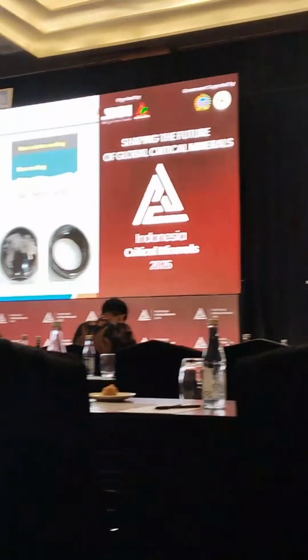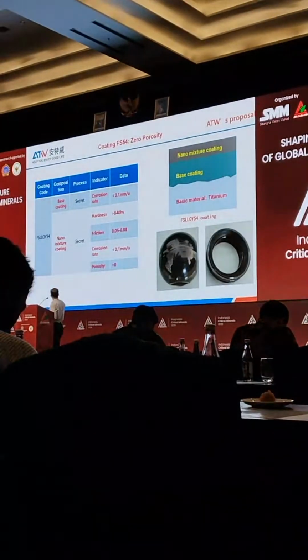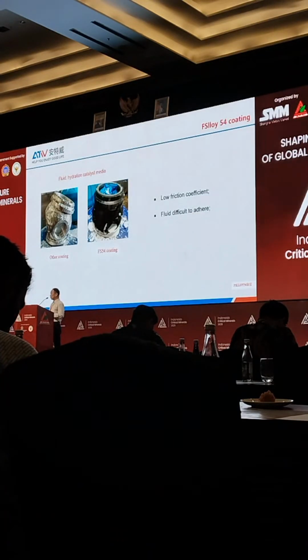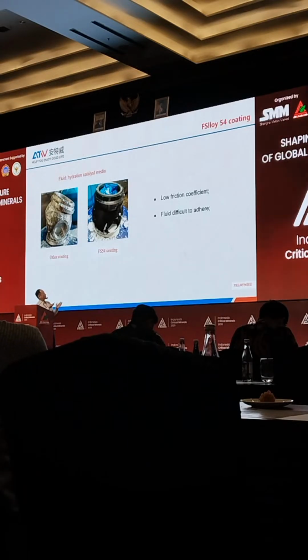And around three years ago, we finally found the coating, which we call FS54. Its corrosion rate is below 0.1 millimeter a year. Its hardness is over 840 HB, and its friction coefficient is around 0.05 to 0.08. And its porosity, the key index, is almost 0. Also, because this coating is a mixture nano coating, it has a very low surface energy coefficient. That means the fluid is very difficult to adhere to the sealing surface of the coating.